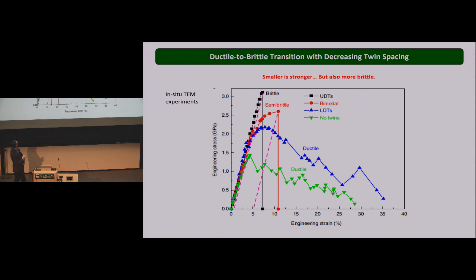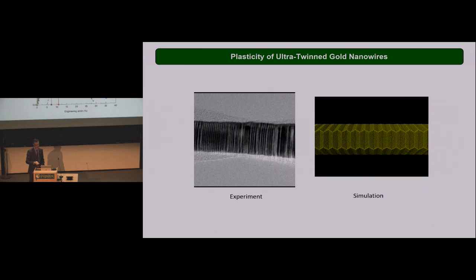And so I have to point out this is gold, and gold is probably the softest metal you can find. You look at the value of stress we measure in situ, on the order of the best ultra high strength material we have. So gold turns into an ultra high strength material on the nanoscale. That's how dramatic the change is. So these materials are brittle, and this is obvious when we look at the simulation.